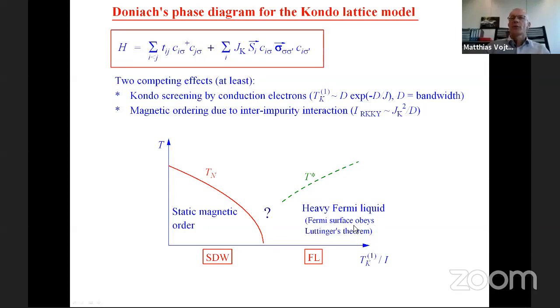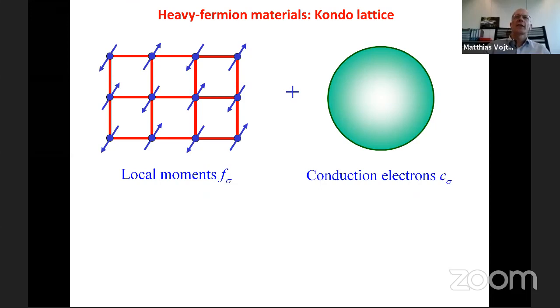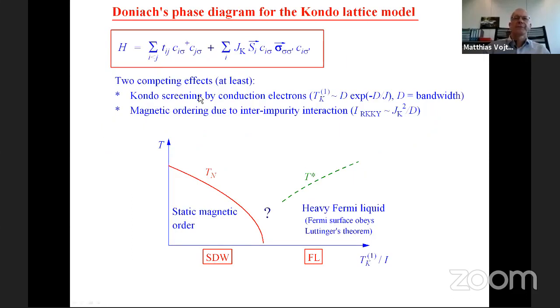Importantly here, the Fermi surface obeys Luttinger's theorem, which means that the volume of the Fermi surface is given by the total number of the electrons, which importantly in this case is the number of these electrons plus the number of these electrons, which means if the Kondo effect is in place, then these localized electrons effectively become itinerant. Okay, so what this phase diagram does is it reflects the competition between local moment interactions and metallicity. Now, what I told you before is that there is such a thing as a spin liquid, namely this static magnetic order, which exists here on the left-hand side, can also be destroyed by frustration.